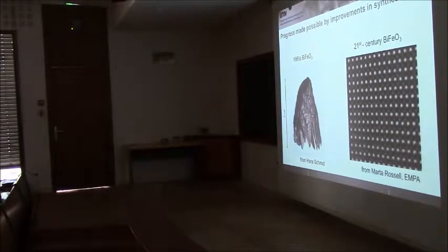This is a high-resolution TEM image of one of Ramesh's films, 21st-century bismuth ferrite, from Marta Rossell at EMPA. You can see that at least on the scale of this image, these are the bismuth atoms, spaced 4 angstroms apart. The films are essentially perfect. So this development in synthesis enabled the identification of new multiferroic materials. Okay, questions?